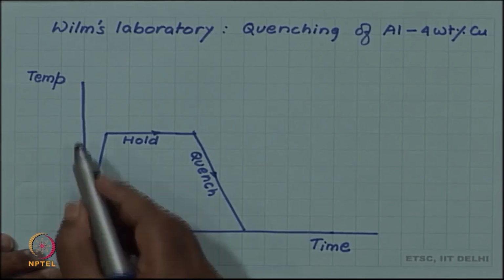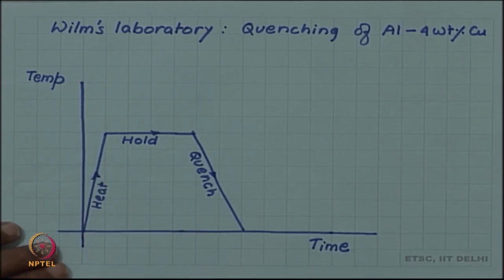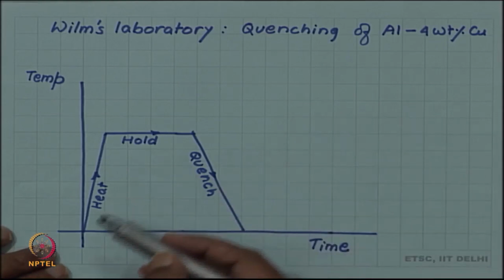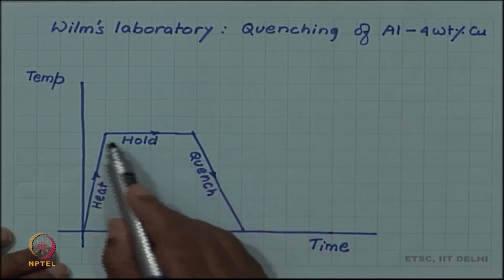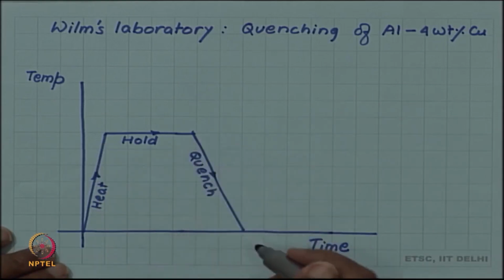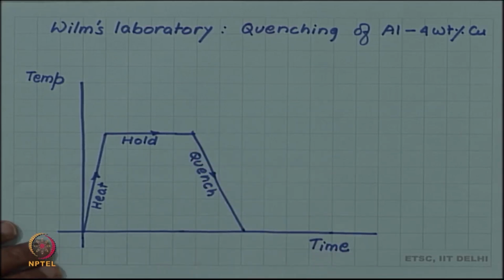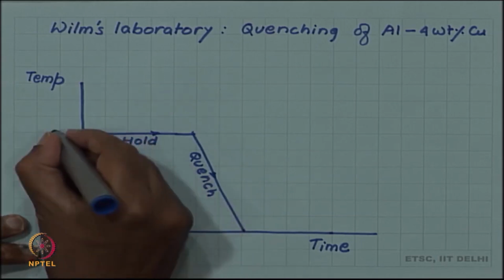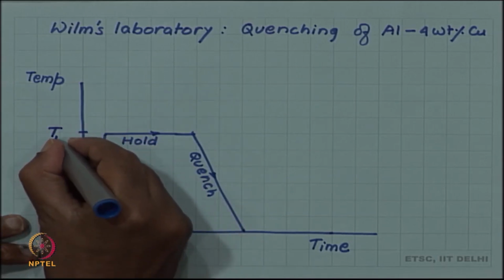So, as you know, a temperature and time graph can be made for any heat treatment process. So, he planned to heat the aluminum alloy, hold it and then quench it, and after quenching measure the hardness. And the expectation was that like steel, maybe the hardness of the aluminum alloy also after quenching will increase. So, this is the temperature for holding.